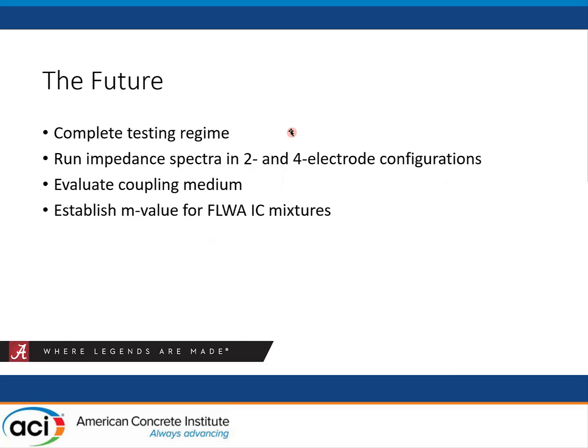And so our future plan, well, we're going to complete this testing. We're going to run this impedance not only in the 2 electrode configuration, which is top and bottom using the plates and saturated sponges. We can actually hook up our impedance analyzers to measure a 4 electrode configuration, which represents the surface resistivity measurements we could take.